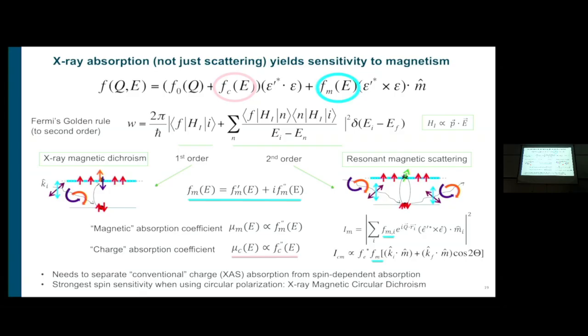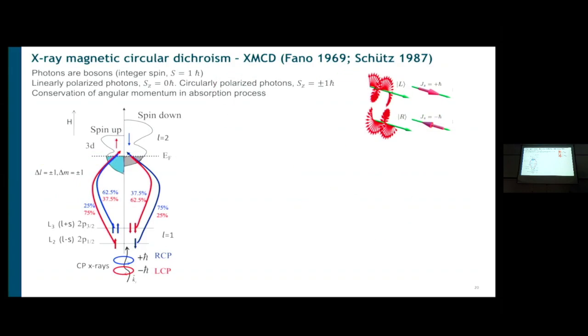It's magnetic dichroism, and it turns out that if you use circular light and you measure the difference in absorption for left and right helicities, which is the X-ray magnetic circular dichroism, it's the most sensitive to the spin in the atom. So I want to say a little bit about X-ray magnetic circular dichroism.